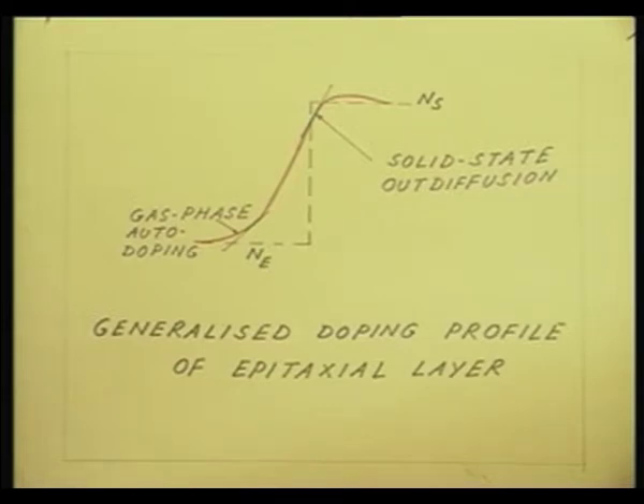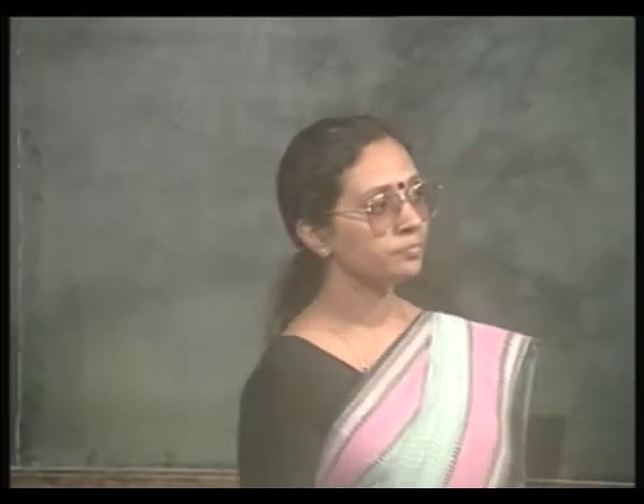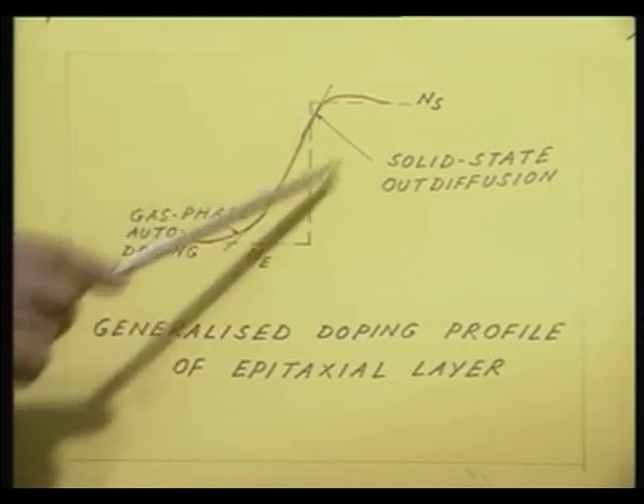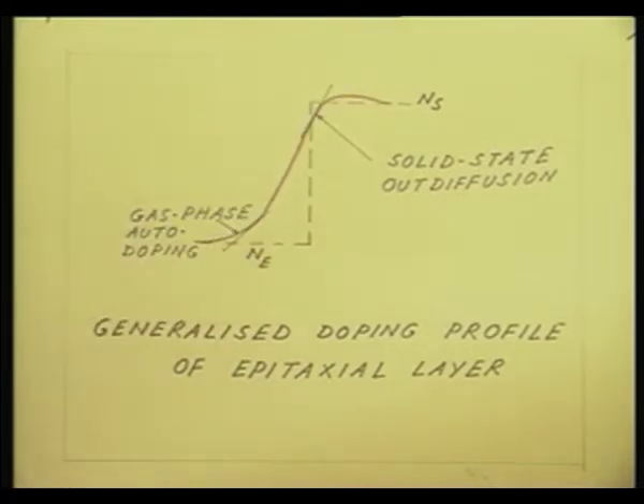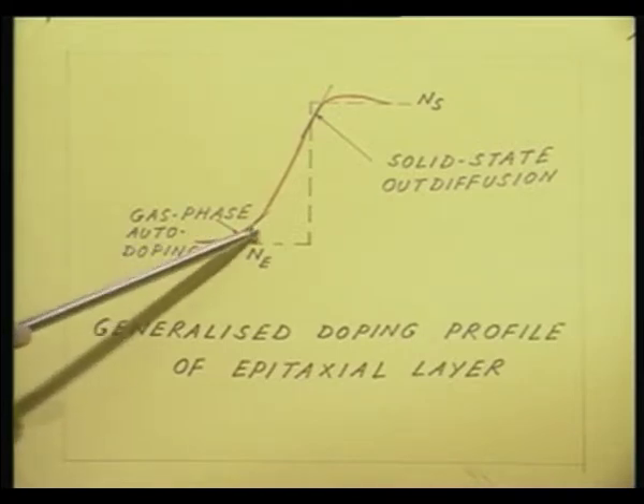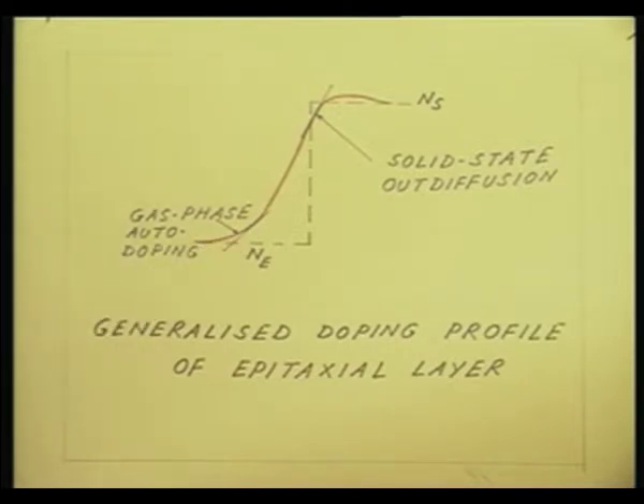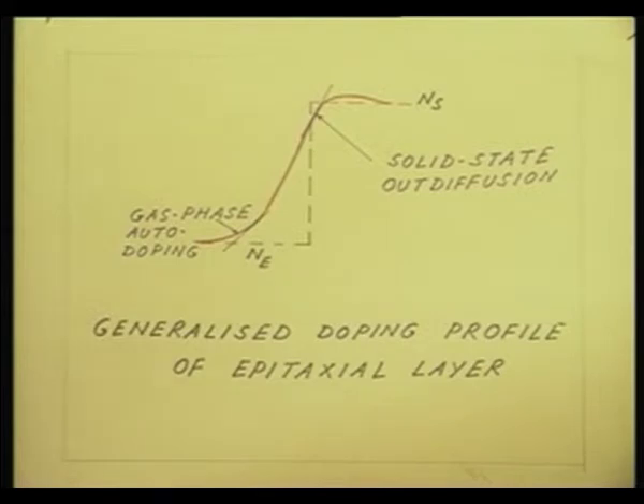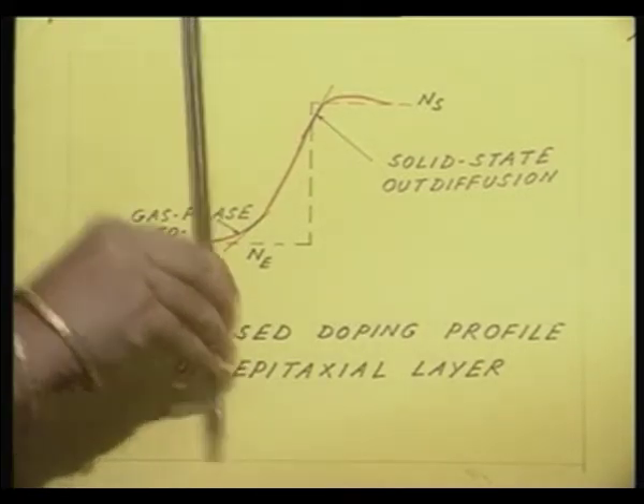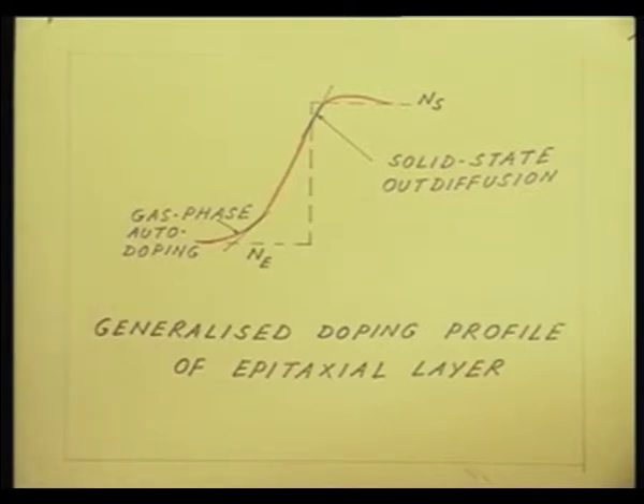Now, in this particular example, I have chosen the epitaxial layer and the substrate to be of the same type. Let us say the epitaxial layer is N type, the substrate region is N plus. So, what I have is just this extended transition region, and that actually determines how thin an epitaxial layer I can grow with the proper Ne doping concentration. You see, from this figure it is obvious that up to this is my transition layer, and only after that I have the epitaxial region with the proper doping concentration.